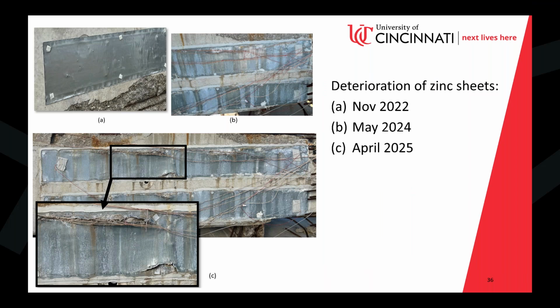Within the time period we looked at here, the zinc was starting to crack and peel apart. This is a little unfair to the product simply because, in this case, because of the open ends, we have a lot of exposed steel here. So this is kind of accelerated timescales. This is not what you necessarily expect to see in the same time if you had applied this to a system that needed a little bit of help, as opposed to just being split open with all that exposed steel. But it gives you an idea of why the strip method might actually work a little bit better. Eventually, if this zinc broke apart and you lost the electrical connection, it would stop the cathodic protection. That wire going to the steel is as important as the zinc being in contact with the concrete.